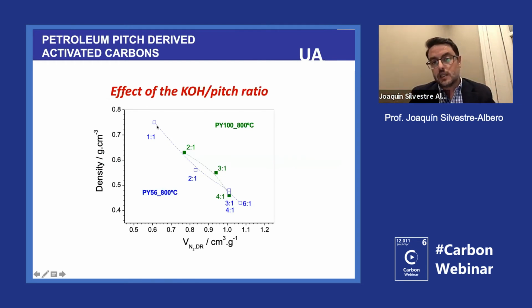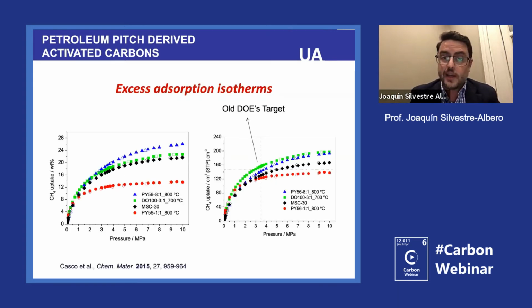As you can see here, the more we increase the amount of KOH, the more you are decreasing the density. And this is clearly reflected here in the final isotherms. These are the excess adsorption isotherms for methane, gravimetric and volumetric. When you look at the gravimetric, as I showed you, with a high amount of KOH, which is the blue one, the 1:8 ratio, you have a maximum in the storage capacity. We are close to 26 weight percent. But when you convert these numbers into volumetric and take into account the density, you can see that the material with only 1:3 activation, the green one, can be the winner of all these materials on a volumetric basis.